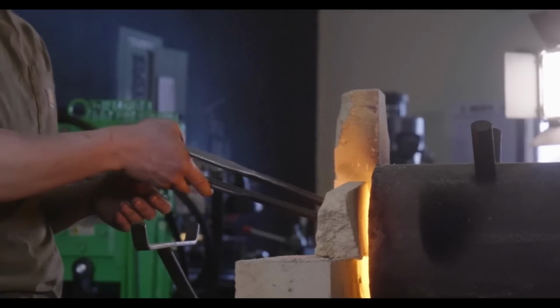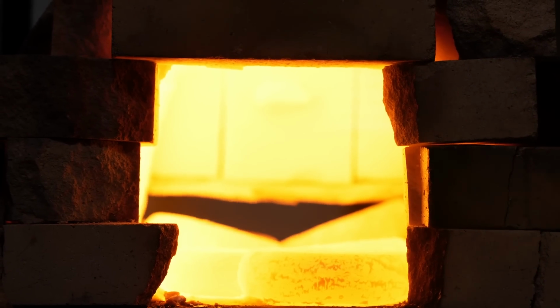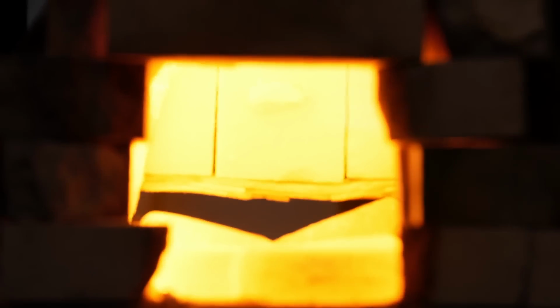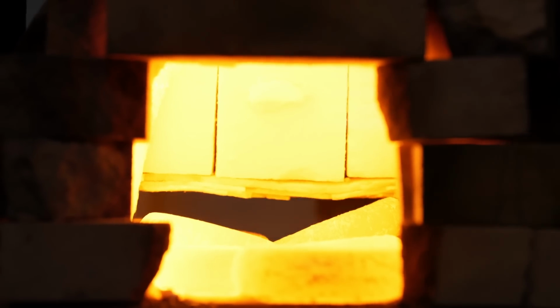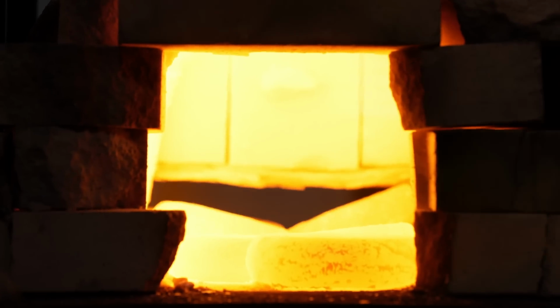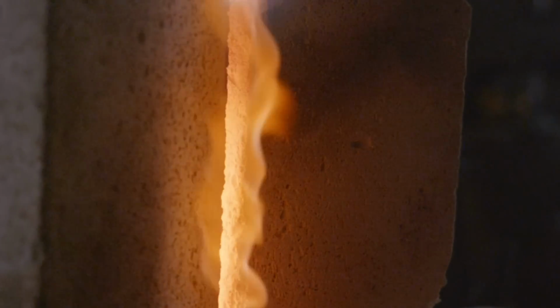And then as long as the atmosphere of the propane or natural gas forge that you're using is what we call a reducing flame, where it has more fuel than oxygen. So the fuel actually has to come outside of the forge to combust. That's where we see the big, what we call dragon's breath coming out of the forge. As long as you have a good reducing atmosphere and your billet is welded up tight, so there's not any big gaps in there, you're actually able to get away without any sheet metal, no argon, no flux, and just